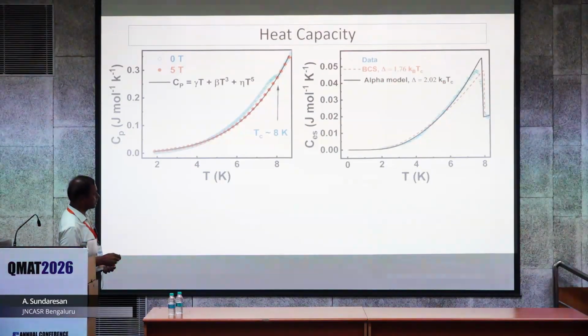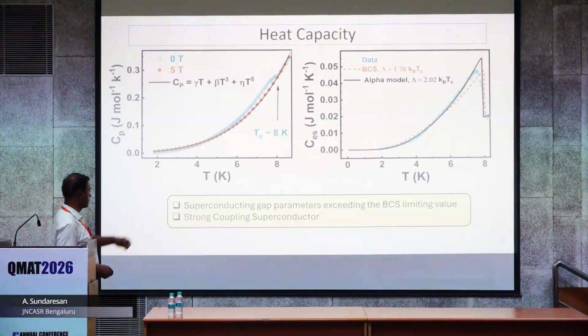What we found is our simple BCS model could not be fitted very well, but we needed an alpha model to vary n. What we get, delta is 2.02, roughly 2, indicating a strong coupling superconductivity in this system.